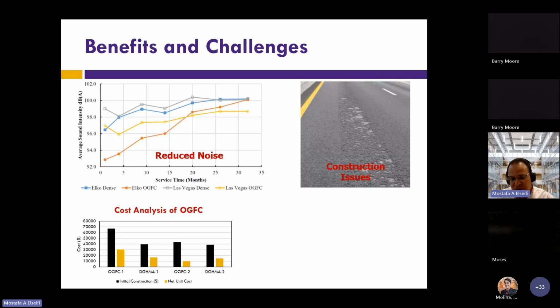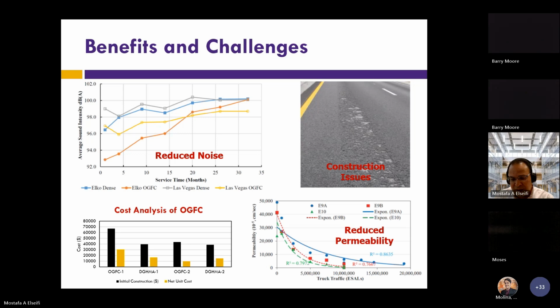In terms of construction, again, the mix is very thin, and you can end up with some problems after construction. Again, this requires a very skilled contractor that has experience in constructing and compacting this type of mix. And again, the reduced permeability was looked at in the literature. You can see it does decrease over time, mostly due to debris and dust in the air voids, and also because of the consolidation that happens to the mix over time.